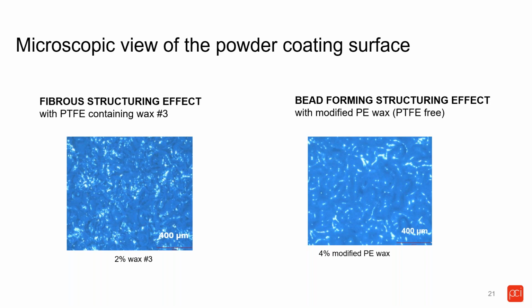Here is some microscopic, if you really want to get down to what the structuring effect is doing. On the left is a 2% dosage of the first wax I introduced that is REACH compliant, regulatory compliant, but still is a blend of PTFE and polyethylene. And then on the right is a 4% dosage of the one that we just reviewed, that is the PTFE free wax. So to the extent that you're really trying to get down to not only what the structure looks like to the naked eye, but what the structure is doing underneath, this shows you the difference between a fibrous and a bead forming structure effect. That's really where that visual appearance is coming from.